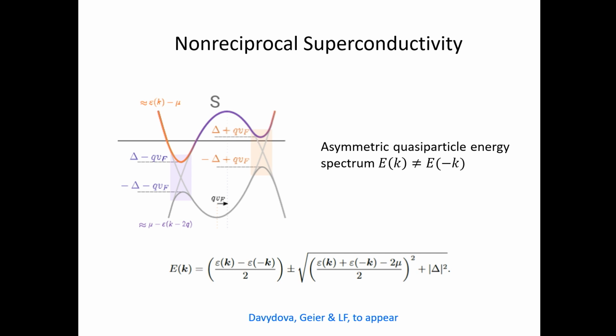So that's why recently we started to think about a better way to probe non-reciprocal superconductivity. This is work with my student, Margarita Davidova, and the new postdoc, Max Geier. And the idea is that instead of thinking about the property of a superconductor under a large applied current, we think about its property in equilibrium. One of the most fundamental properties of a superconductor is the quasi-particle energy spectrum. And we all know that when pairing occurs, the states near the Fermi level acquire an energy gap. What is shown here is a quasi-particle energy spectrum as a function of momentum. Now, usually this gap is symmetric, k to minus k, and this is for conventional superconductors.